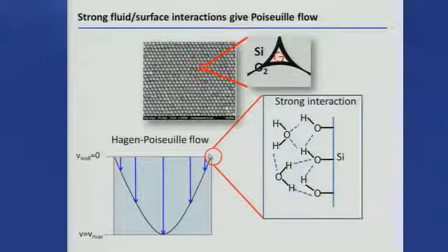So the reason why the velocity would go to 0 at the wall is because when the molecules go to the wall, they'll interact. If you've got a silica wall, which has hydroxyl groups and has a layer of stationary water on it, a molecule can bump into this, have a hydrogen bonding interaction, which makes it stop for some short period of time, and then it will leave again. So molecules reaching the wall will stop if they have some attractive interaction with the surface.